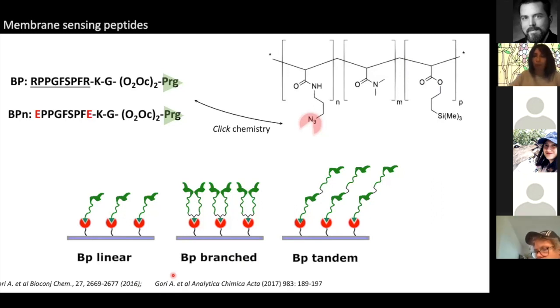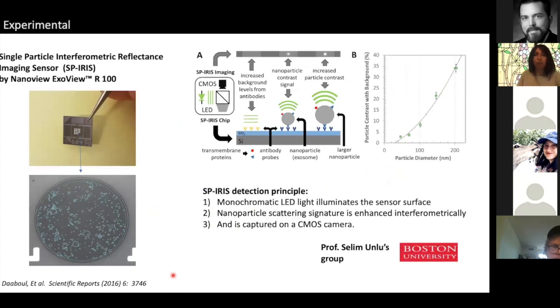Well, the detection platform that we use is the ExoView platform by NanoView, that, as you might know, is based on a technique called single particle interferometric reflectance imaging sensor, SP-IRIS. This is a label-free technique which is able to make use of these silicon chips that are spotted in the center with the spots of capturing probes, in our case peptide probes. The instrument images each spot and is able to label-free detect, count, and size the single vesicles that are captured on the surface.